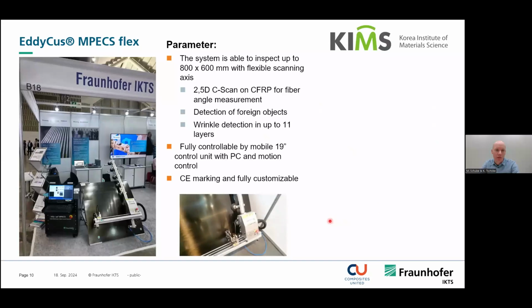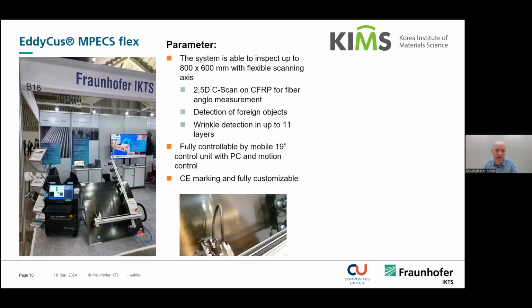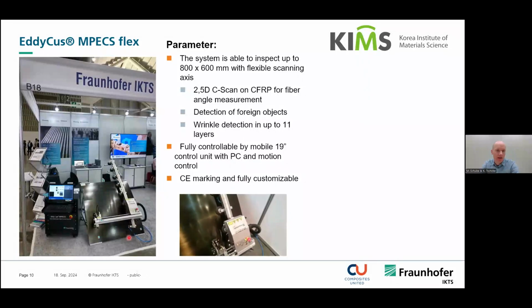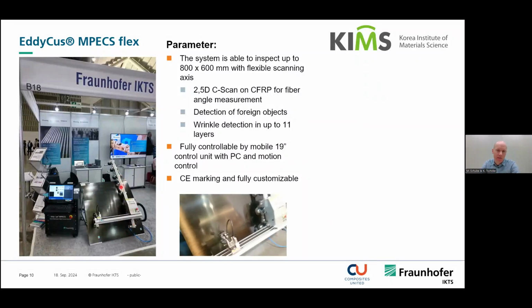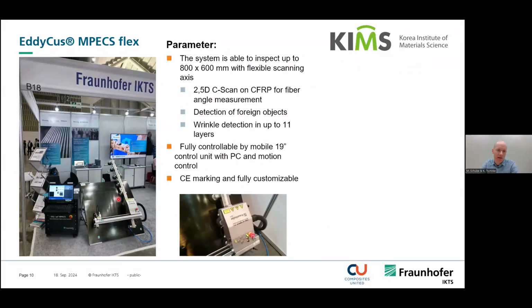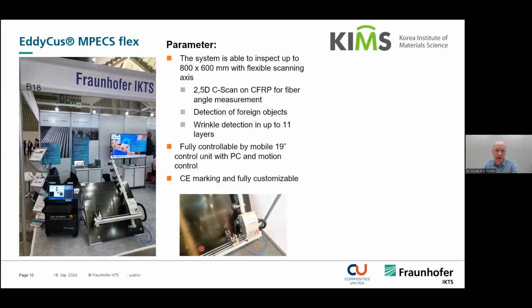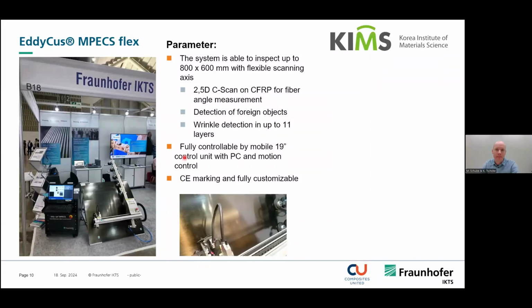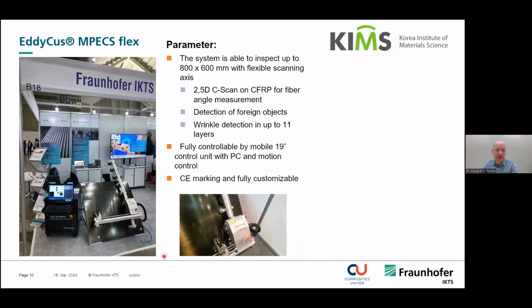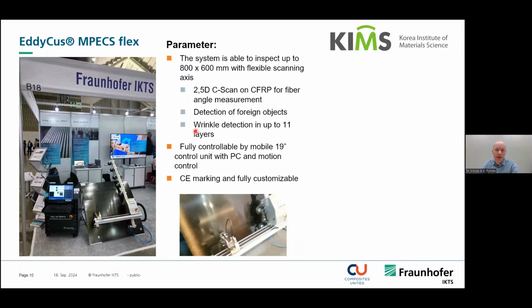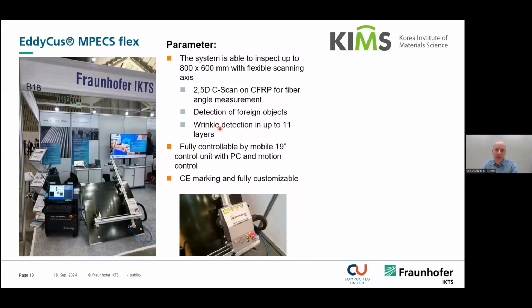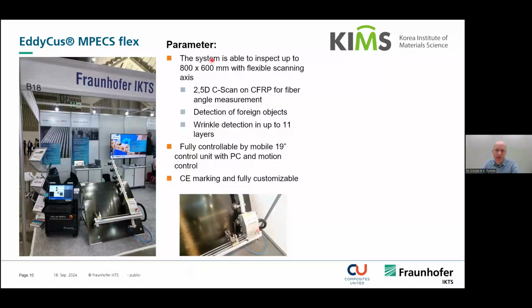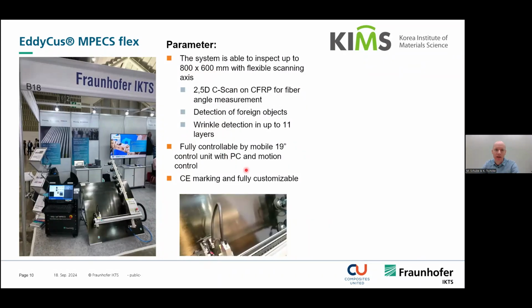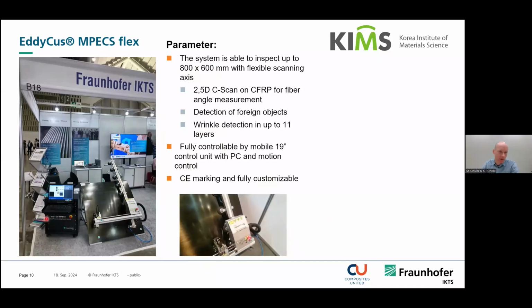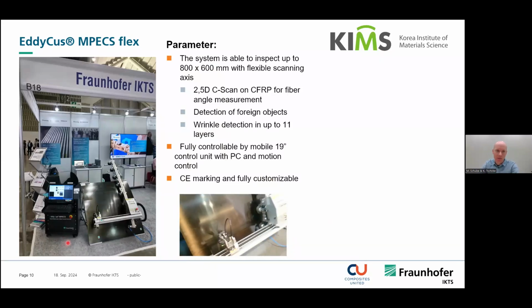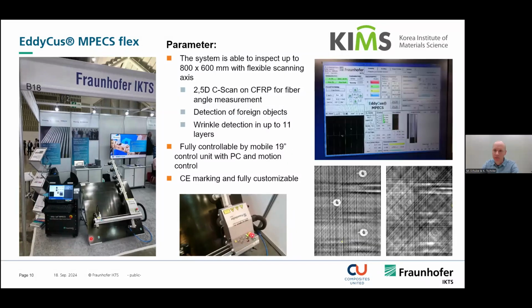The shown devices were modified even to such a flexible scanner. Its main feature is the possibility to suck onto a structure, and then you can obtain an eddy current C-scan. With this type of device, we are able to monitor wrinkles and gaps in up to 11 layers. The device is able to scan 800 by 600 millimeters and has this nice control cabinet, so you can use it in the laboratory or even in the field. And here we see some examples.